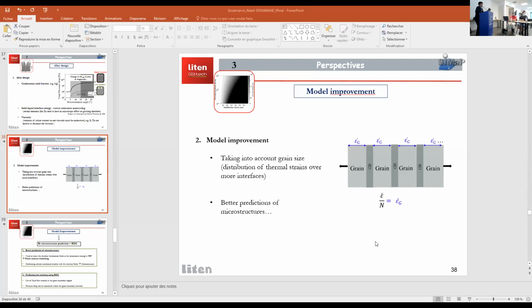The two major directions: surface active elements to play on the coalescence and grain structure. And of course, it's not in the RDG. RDG is a two-phase continuum description. You know, very simple. Consider delta P as a hot cracking sensitivity. The higher, okay. That's why we reach such high values, which is almost nonsense, maybe.